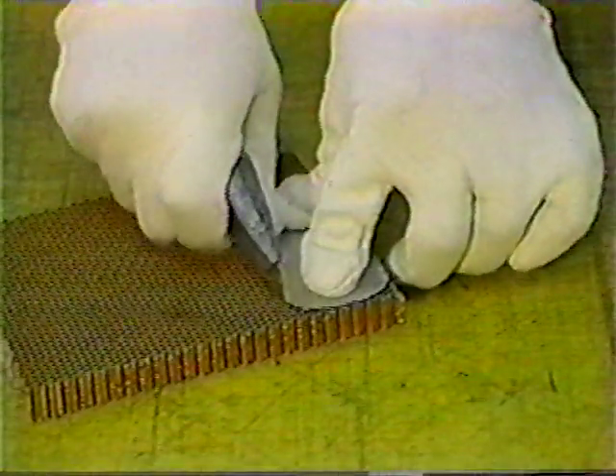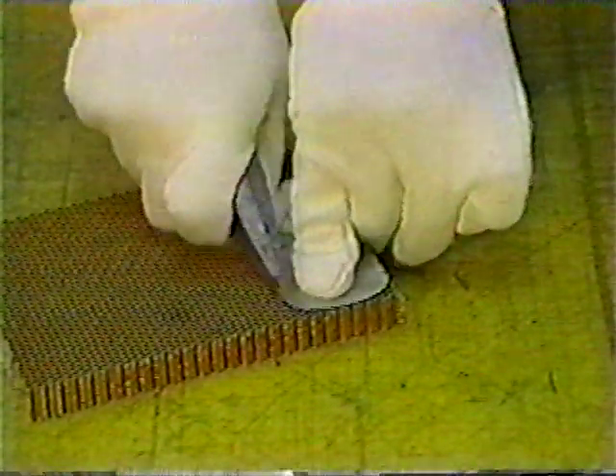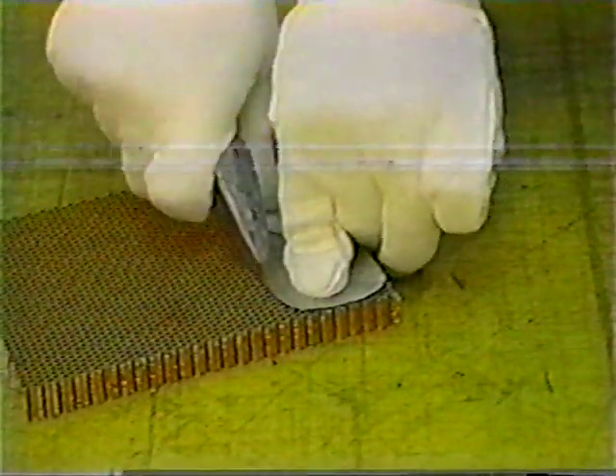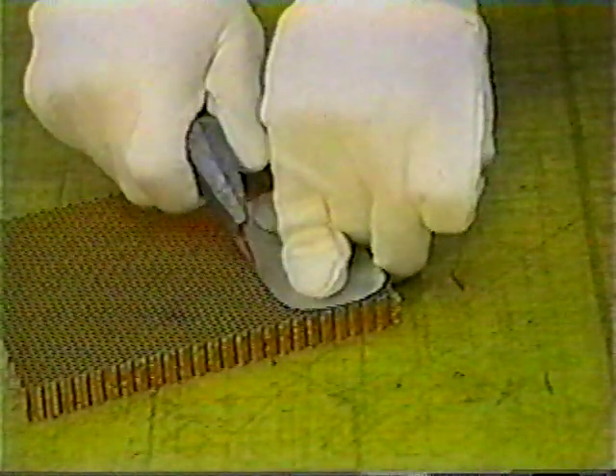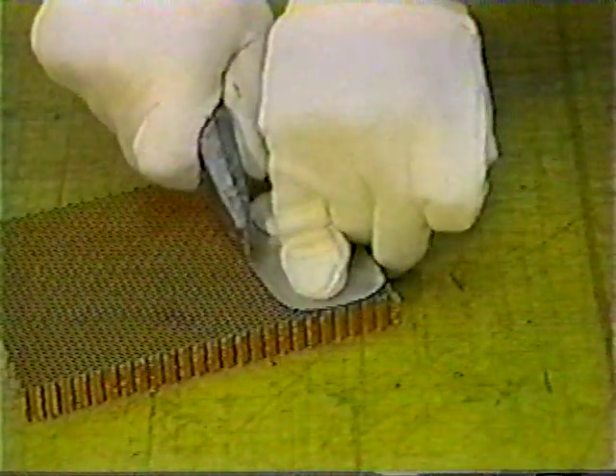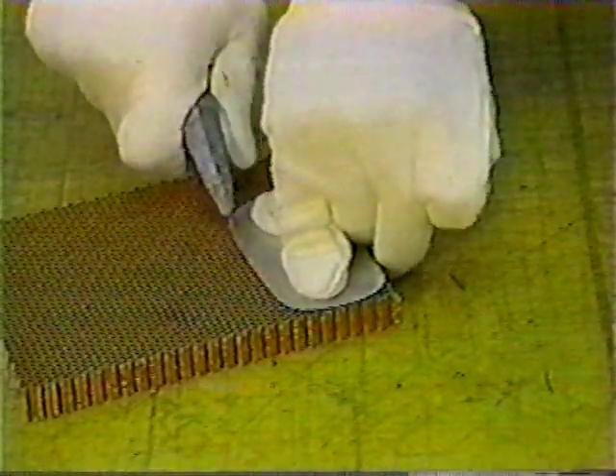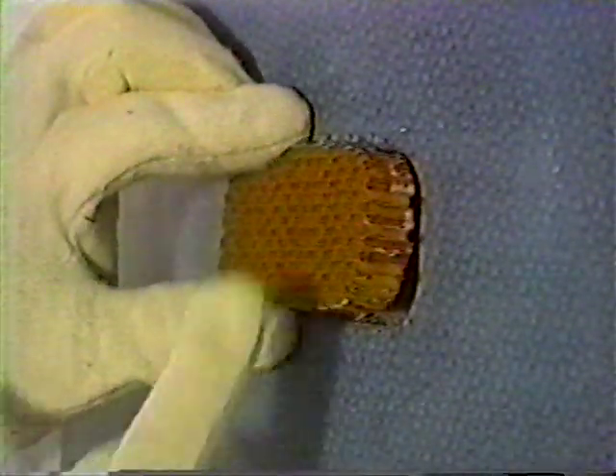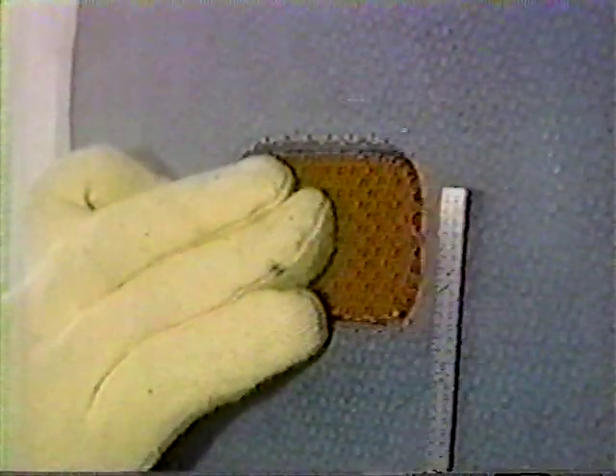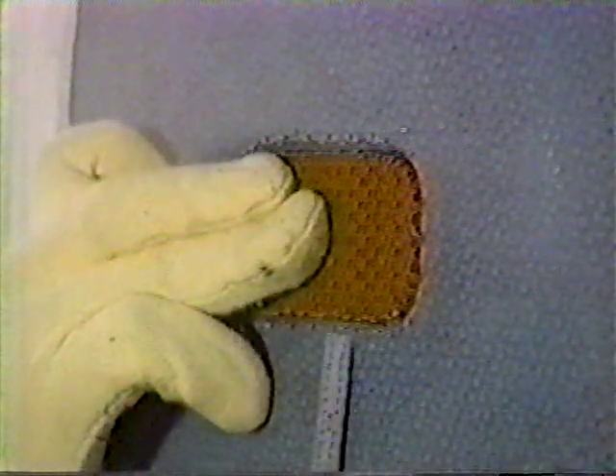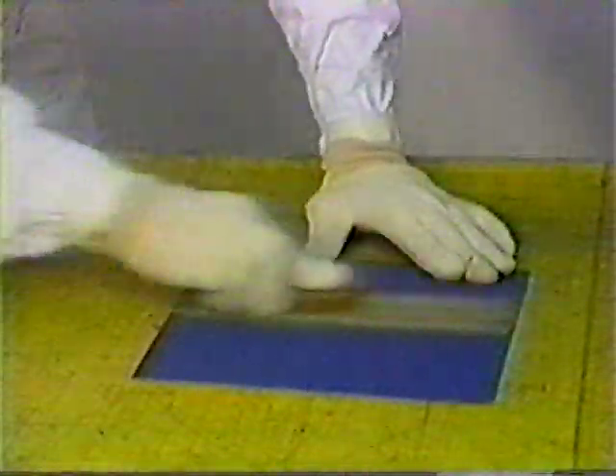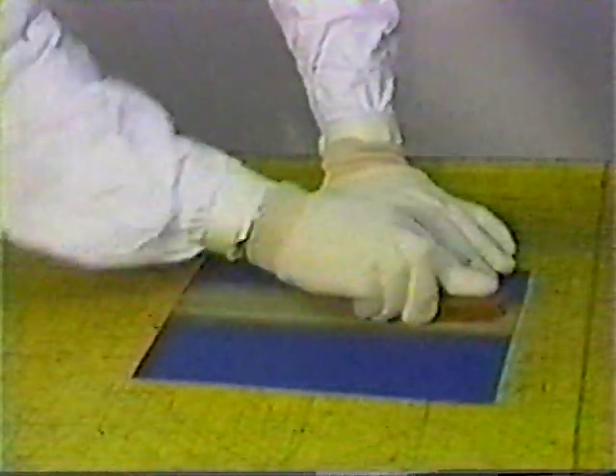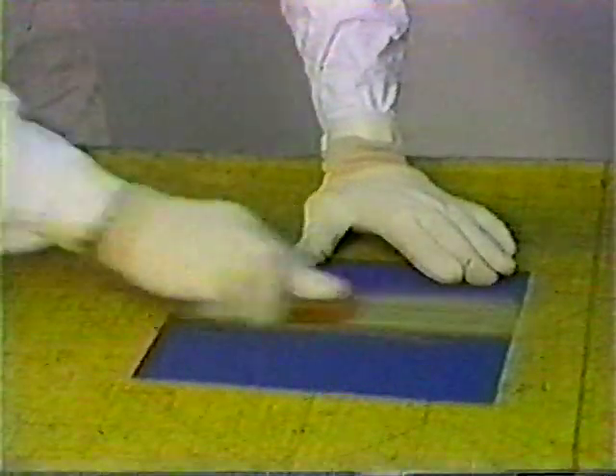After determining the type and the dimensions of the honeycomb core in the panel, cut out a core plug so that the ribbons of the plug match the direction of the ribbons of the surrounding core in the panel. Next, insert the core plug into the repair area. If the core is riding too high, as seen here, it will be necessary to trim the plug slightly to make it the same height as the surrounding honeycomb.